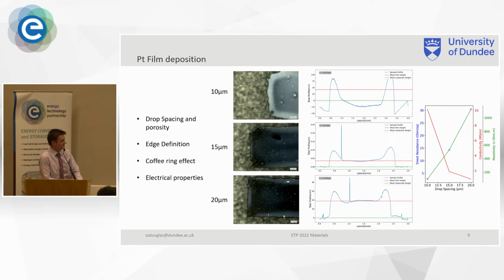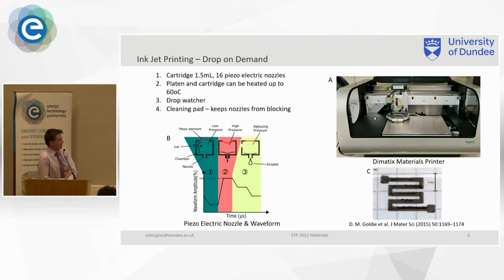Okay. You mentioned voltage and piezoelectric. What does that mean? How are they related? What's that got to do with print speed, droplet speed? So the voltage that you apply to the piezo element controls the force, the pressure that is applied to the ink within the nozzle. So in the waveform, you reduce it to 0, which creates a low pressure, and draws the ink into the nozzle. You ramp the voltage up to 100%. You set that voltage dependent on the velocity you measure afterwards. That pushes the ink out at that velocity.